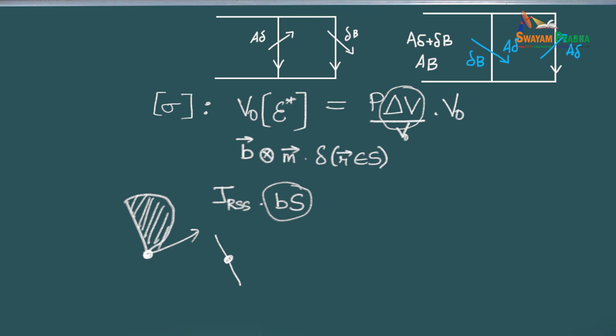If you have a small activation volume, it means that the dislocation does not bend much before it unbends. High activation volume means large bending. So it has to do with the density of defects, but also with the strength, the pinning strength of the defects.